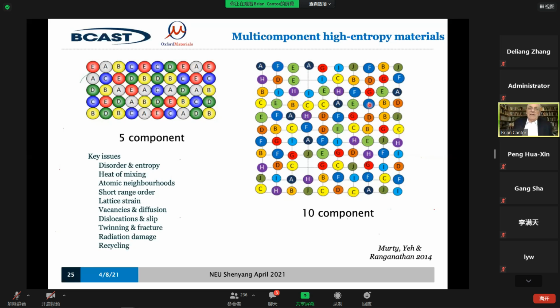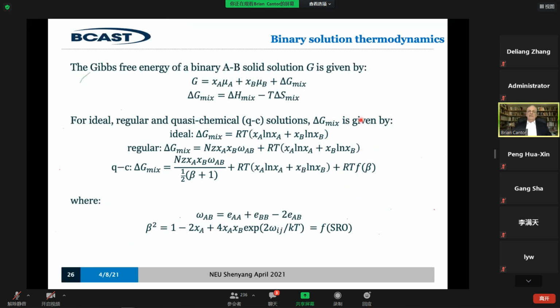So here's binary solution thermodynamics. I don't want to bore you with too much maths, but you should understand this. The free energy is the sum of the chemical potential for a composition XA and XB. The binary material is the sum of the chemical potentials of the materials A and B before you mix them, plus a free energy of mixing. The free energy of mixing depends on the enthalpy of mixing and the entropy of mixing. If it's ideal, there is no enthalpy of mixing, and the only entropy of mixing is the random distribution of the A and the B atoms, and that's got that entropy there. So that's the core of the entropy that we're going to be interested in.